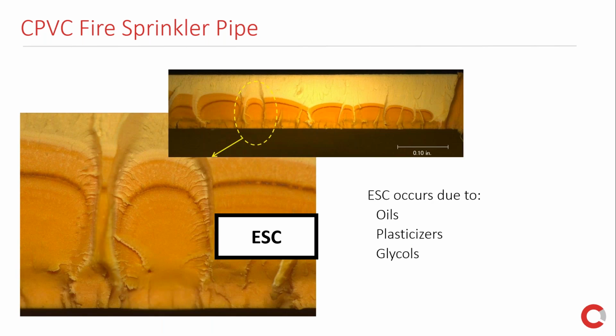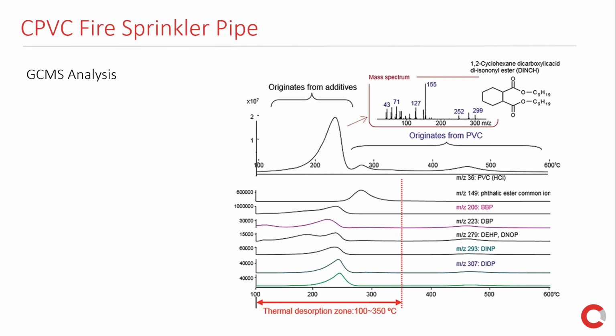In CPVC pipes, ESC is typically created by incompatible oils, plasticizers, or glycols, and it creates a fracture pattern that is similar to what you see here on these images. So in many cases, visiting the site and identifying the potential source of these compounds is critical for every investigation. In this case, the analysis of the fracture surfaces using GCMS detected incompatible glycols, which were likely originating in the antifreeze solution used. As I mentioned before, analysis via GCMS detected the presence of incompatible glycols, and these glycols were traced back to the antifreeze solution used by the fire protection contractor.